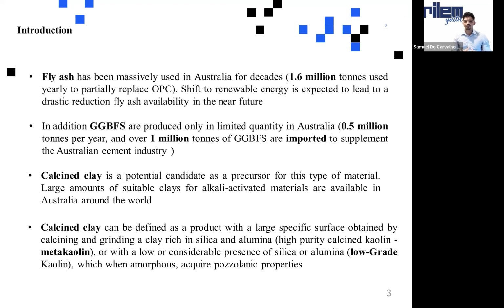Same case for GGBFS, or slag. In Australia, around 1.5 million tons are used, for the same reason as fly ash, to replace OPC and in some small applications, but only around 0.5 million tons are produced in Australia, and 1 million tons of GGBFS is imported from overseas. Because of this, we're looking for new raw materials to produce alkali-activated concrete and also low carbon concrete to replace OPC.